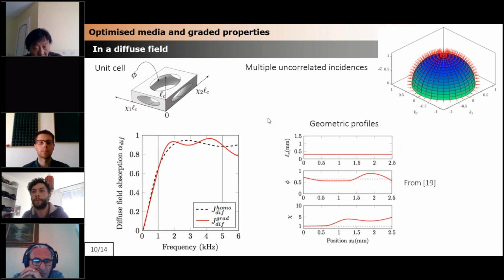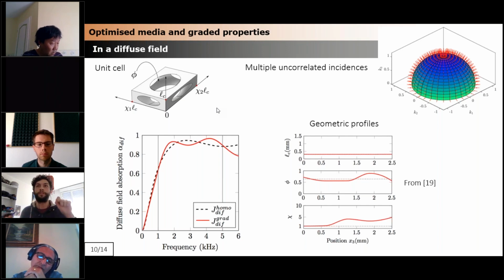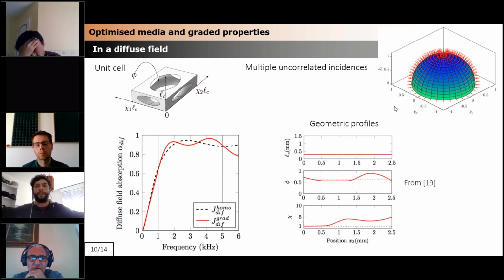One more thing we can cover with these optimization techniques. If you remember, on the top left corner you have the previous unit cell that I presented in the beginning, which is pretty simple to design, and to introduce anisotropic properties you can control the geometry of this unit cell by the stretching factors, which I denoted chi1 and chi2, which give you a simple anisotropic tuning. Instead of considering only the normal incidence, you can have, for example, on the top right corner, 400 incidences impacting a finite layer thickness, which is infinite in all the other dimensions. We can optimize the average absorption and diffuse field absorption coefficient with the same optimization techniques, but this time considering anisotropic properties and graded properties in the material.